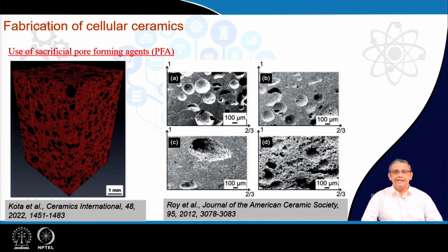In this case the size of the polymer waxes was varied, and two different types of polymer waxes were used. One had a spherical shape with coarse morphology, and the other one was a fine shape with kind of uniform morphology, and as you can see, these give rise to very well defined and varied morphologies.